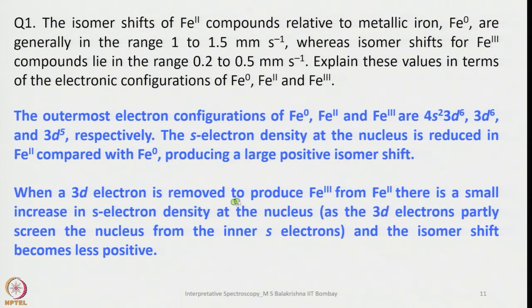When a 3d electron is removed, from 3d6 to 3d5 going from Fe2 to Fe3, there is a small increase in s electron density at the nucleus. As the 3d electrons partly screen the nucleus from the inner s orbital, the isomer shift becomes less positive. That's the reason the change between 2 and 3 is less significant, because no s electrons are involved in it. It's only taking out one d electron, whereas in case of Fe0 to Fe2 or Fe3, we are talking about s electron density. That shows how the s electron density influences the isomer shift.